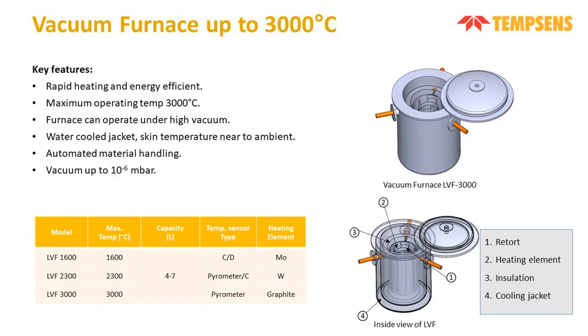Our standard vacuum furnace has around 4 to 7 liters of capacity. For the thermocouple sensors, in contact type we have C type thermocouple, and in non-contact type we have pyrometers. Accordingly, we select the heating element according to the temperature and the environment in the furnace. For 1600 we have gone for molybdenum, for 2300 we have gone for tungsten, and at 3000 degrees Celsius we go for graphite type heaters.